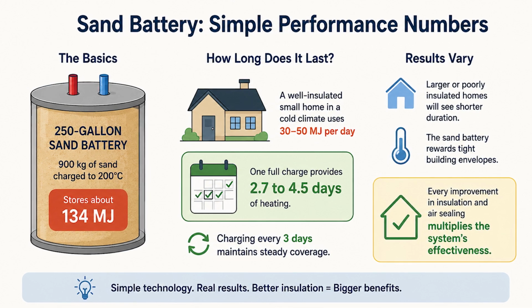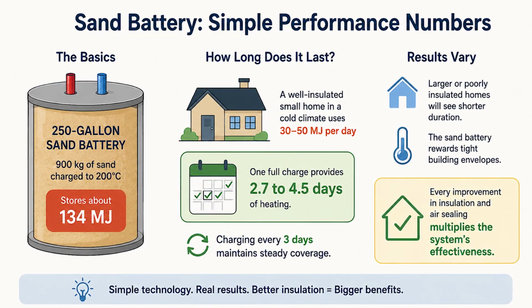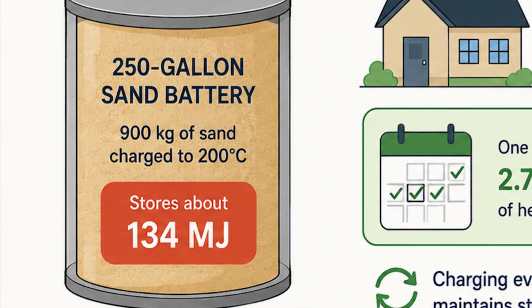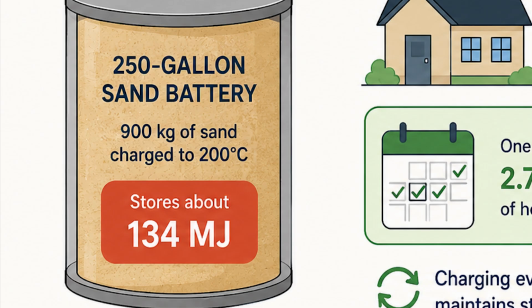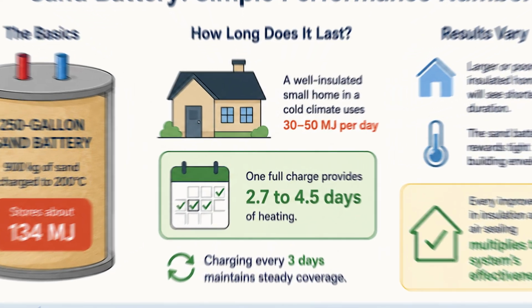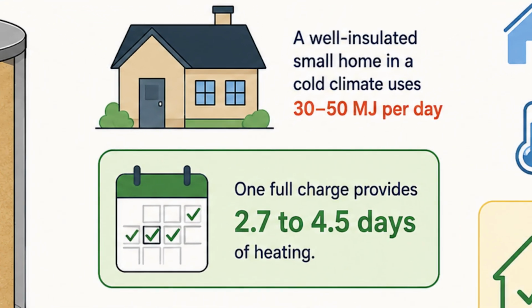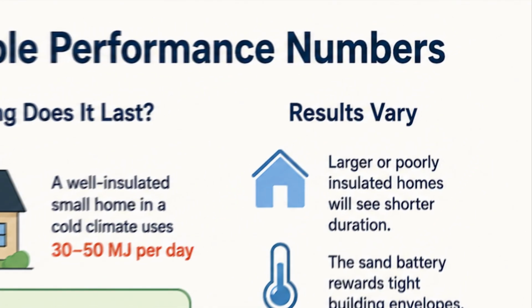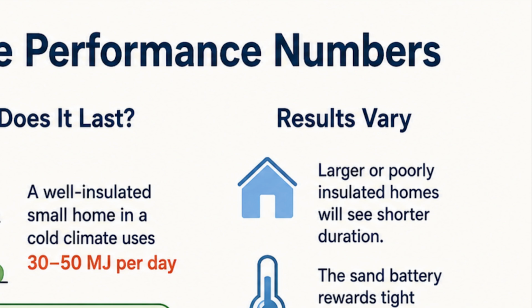Performance numbers are important for realistic expectations. A 250-gallon sand battery with 900 kilograms of sand charged to 200 degrees Celsius stores about 134 megajoules. A well-insulated small home in a cold climate might use 30 to 50 megajoules per day. This means one full charge provides 2.7 to 4.5 days of heating. Charging every 3 days maintains steady coverage. Larger or poorly insulated homes will see shorter duration, so results vary.